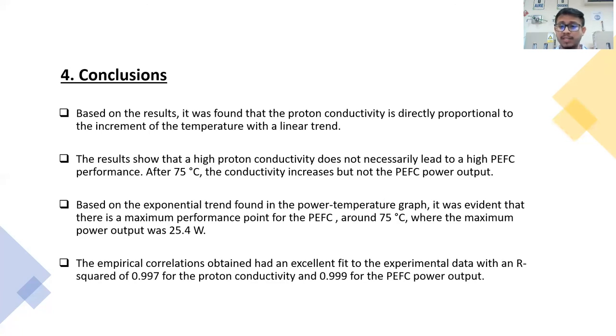After 75 Celsius degrees, the conductivity increased, but not the polymer electrolyte fuel cell power output. Based on the exponential trend found in the power temperature graph, it was evident that there is a maximum performance point for the polymer electrolyte fuel cell, around 75 degrees Celsius, where the maximum power output was 25.4 watts.